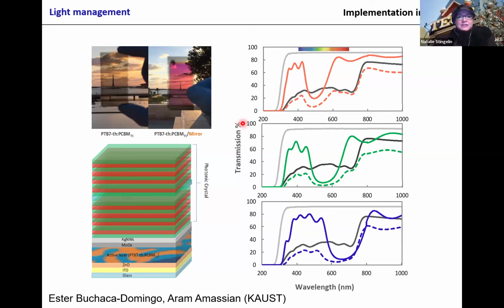So if you look at the transmission of this solar cell, this black line is actually this structure. It tells you the active layer in particular absorbs in the 400 to 700 regime. So you have a low transmission here, and then you have a high transmission. So if you now make different mirrors, and especially like this one, you shine light, the solar cell absorbs, but it doesn't absorb everything.